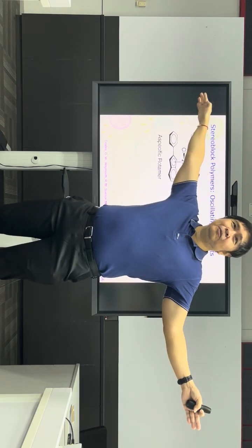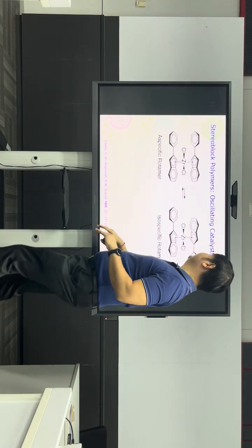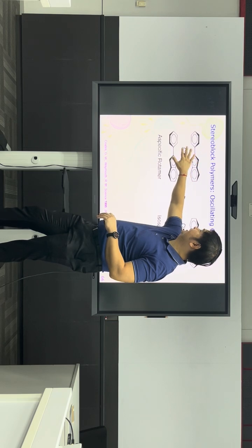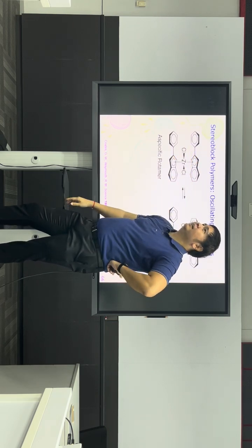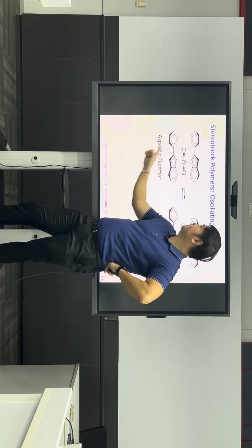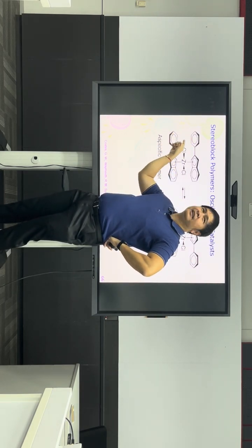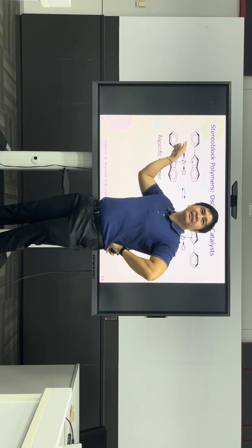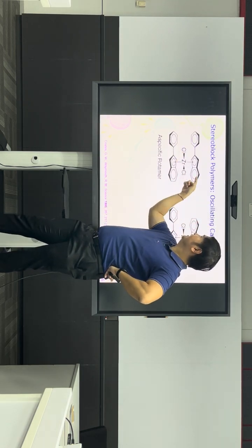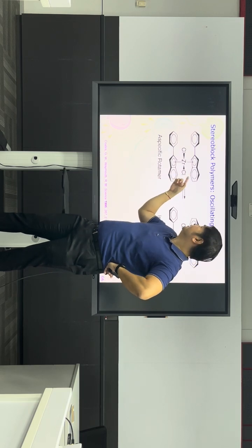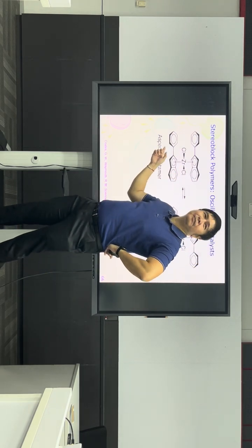It can move around. So what happens if you look at a structure like this one? What would be the polymer produced from this catalyst? If you go to this side, it's the same group, right? Atactic here. If you go to this side, same group, atactic, right? So random basically. So this catalyst will produce random polymer.